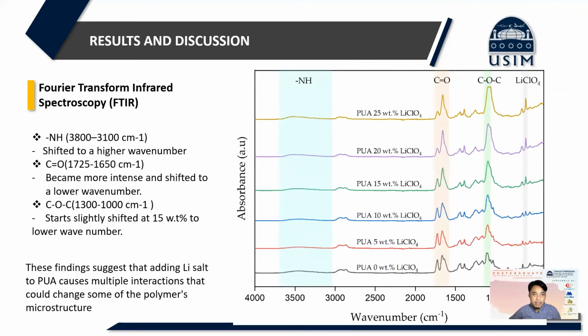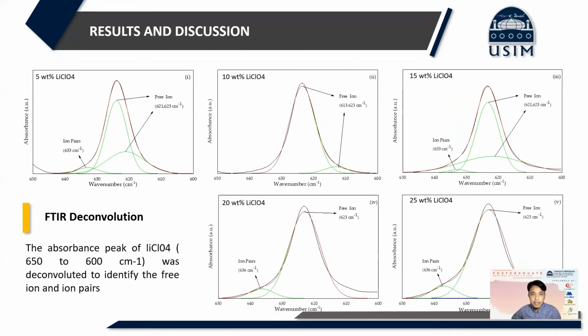For the FTIR, the addition of salt into the polymer electrolyte made the NH group shift to a higher wave number. C double bond O became more intense and shifted to a lower wave number, and C-O-C likely starts shifting at 15% to a lower wave number. It means that these findings suggest that adding lithium salt to PUA causes multiple interactions that could change some of the polymer's microstructure. This is the FTIR deconvolution. The observed peak of lithium perchlorate at 650 to 600 was deconvoluted to identify the free ions and ion pairs.